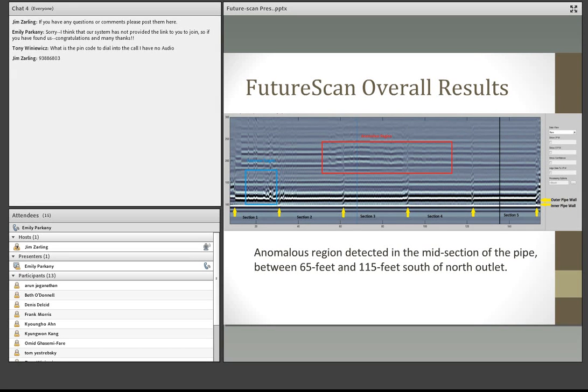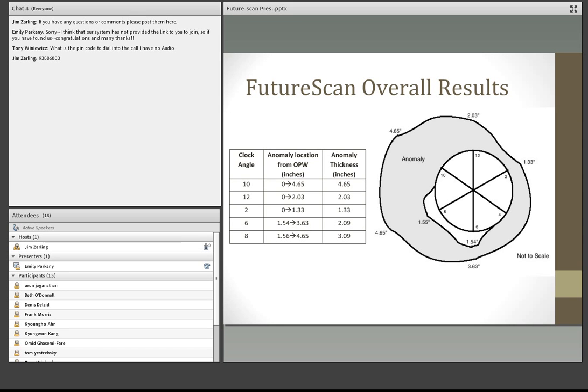And that region was, like I said, pretty large, and it was detected between 65 feet and 115 feet south of the north outlet. And so this region actually aligned fairly well with some of the elevation changes that we saw the day after reaming and at the 4-month mark, with some of the settlements that were noted. If we were to look at a cross-section of this anomalous region, it would look a little bit something like this. And of course, we can only sort of get this information because FutureScan does the 360-degree scan completely around the pipe. So we suspect that that's sort of what that anomalous region looks like.